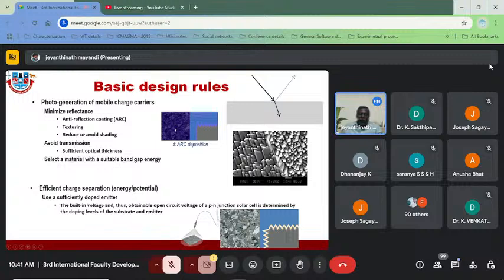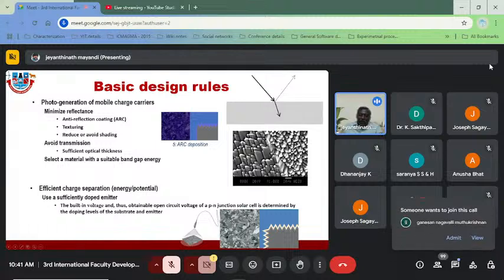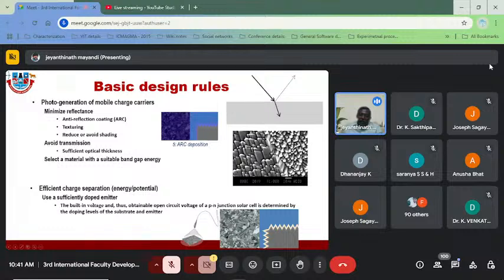Another process is to enhance the absorption. One could also make anti-reflection coatings. After making the pyramidal structure, you could coat silicon nitride on top of it, and this could do two things. One, it will act as an anti-reflection coating, and it will also act as a surface passivation layer. So that is an interesting aspect of these two different techniques. To minimize the reflections, you could use an anti-reflection coating, texturing, and reduce or avoid shading, so you need to calculate how many contacts need to be made. And to avoid transmittance, we should have sufficient optical thickness, with material of suitable band gap energy. So this is the first point.